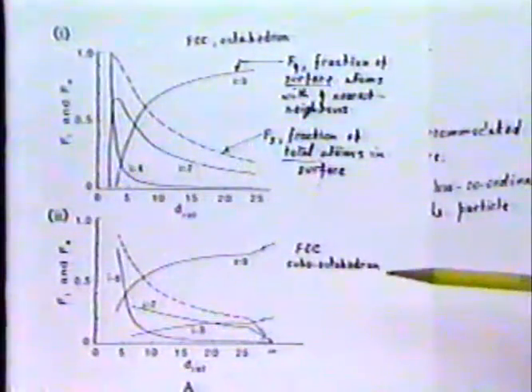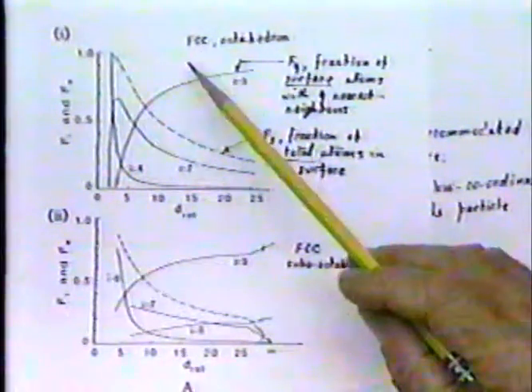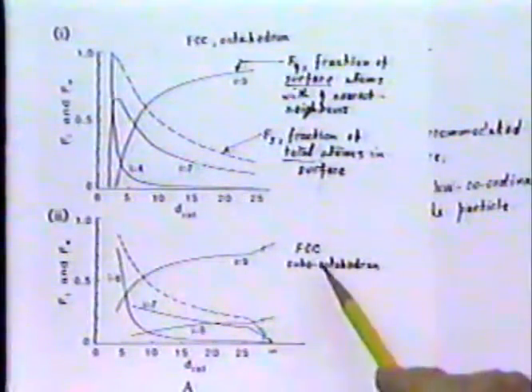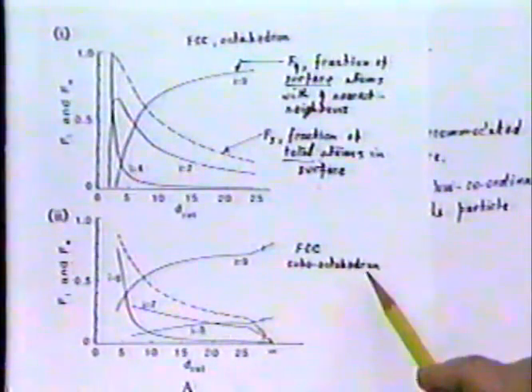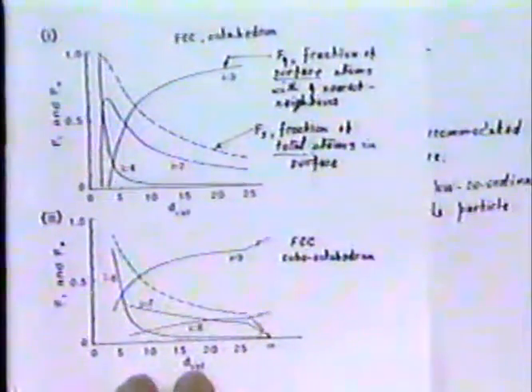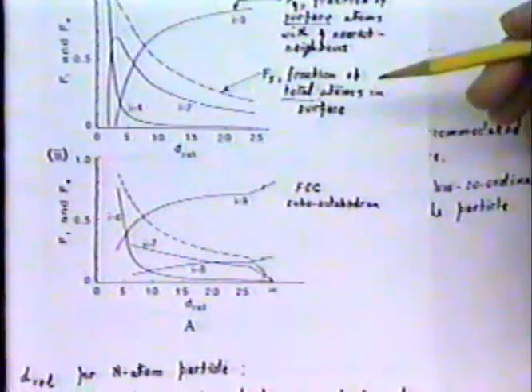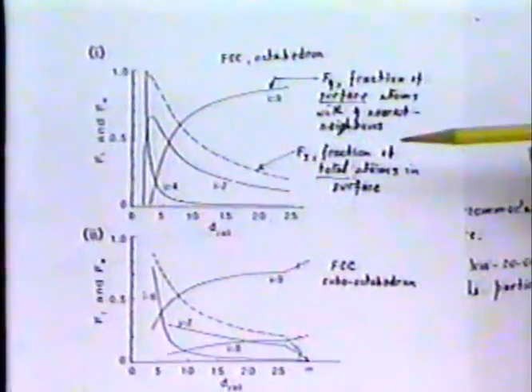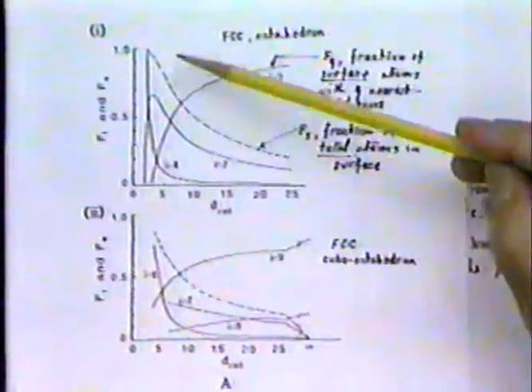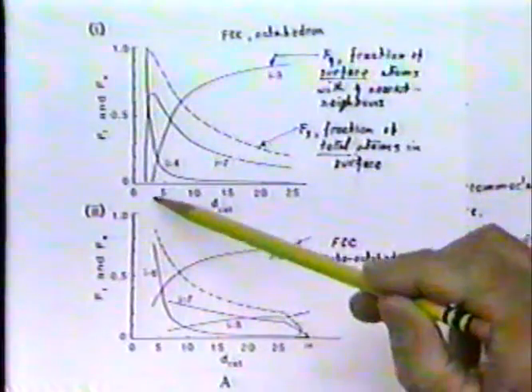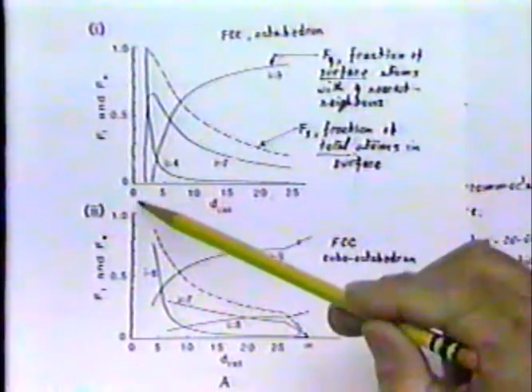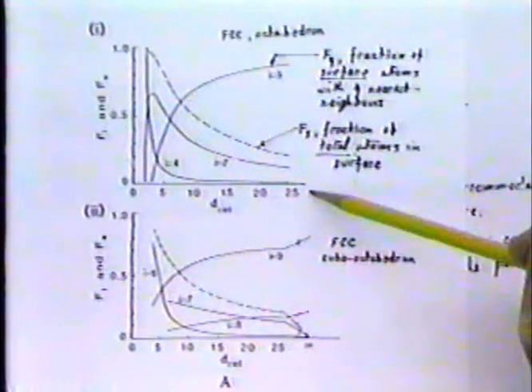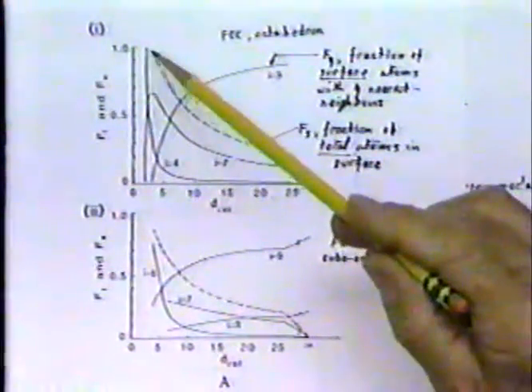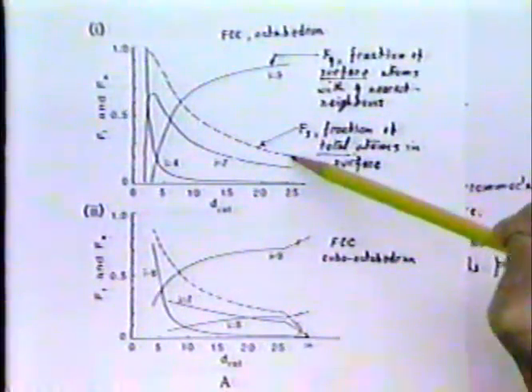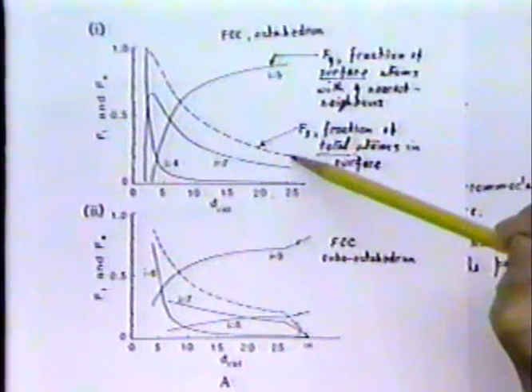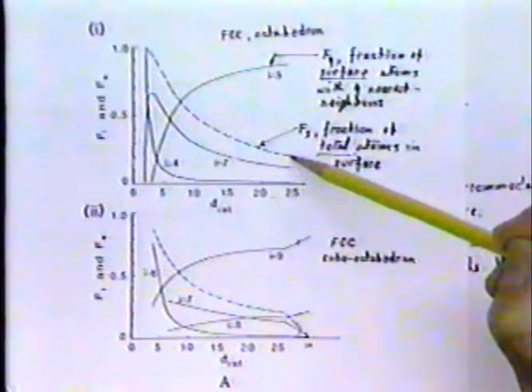Now these two diagrams, both of them refer to face-centered cubic structures. The top one is for an octahedrally shaped crystal. The lower diagram is for a cubo-octahedral crystal, and if you refer back to that previous diagram showing crystal shapes, you'll find both of those shown there under the face-centered cubic classification. And all I want to point out is the obvious, that is to say that as the particle size increases, d relative, and I'll explain what that is in a moment, but it's a dimensionless parameter for crystal size, as the crystal size increases, of course, the fraction of the total number of atoms present in the surface decreases and goes to 0 when the crystal size is infinitely large.